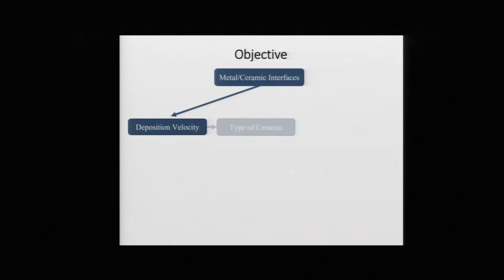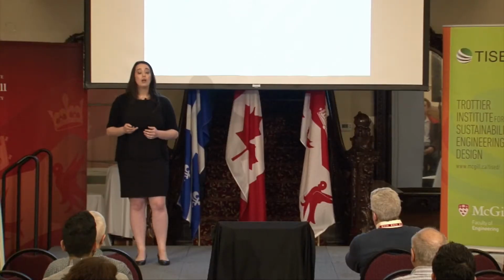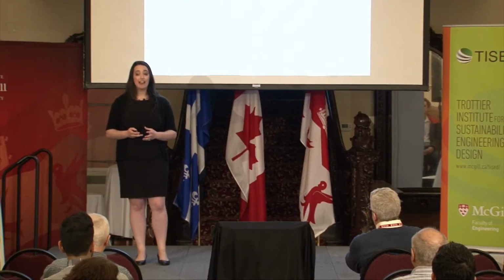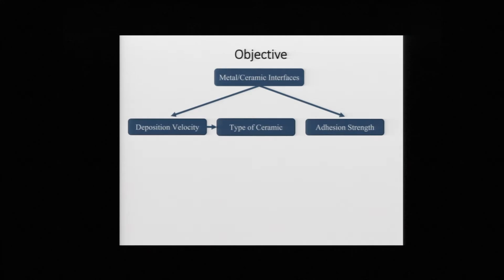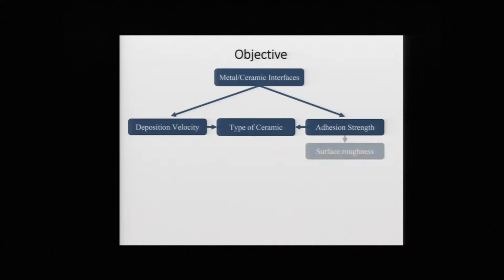And we study this by changing the ceramic and seeing how the type of ceramic that we're using will influence the critical velocity for deposition. But once these particles have been deposited, we need to know how well are they bonding? How good is that adhesion strength? And once again, we study this by looking at how the type of ceramic will affect it, and also how surface roughness could affect it.